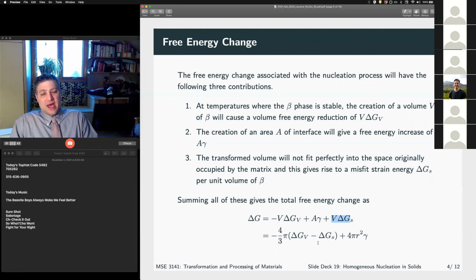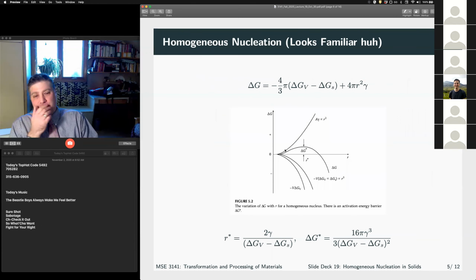Okay, so we have our volume terms where our strain subtracts from our bulk plus our surface energy. So what does that look like? Well, here's our volume term, here's our strain term, our surface energy term, and this is exactly the same as for nucleation of a solid from a liquid, but now we have a reduction in our driving force due to the strain, right?